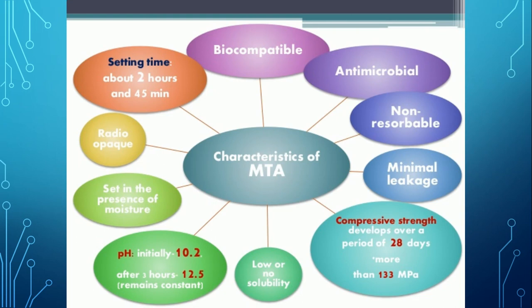Properties of MTA: it is biocompatible, antimicrobial, non-resorbable, and has minimum leakage. MTA has compressive strength that develops over a period of 28 days to more than 133 MPa. It has low or no solubility. Initial pH is 10.2, reaching up to 12.5 by 3 hours and remaining constant. MTA sets in the presence of moisture. It is radiopaque and setting time is about 2 hours and 45 minutes.